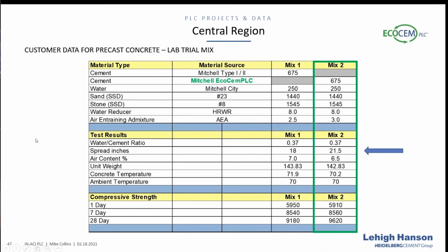This is a trial mix that we did in our lab at the request of a customer, where we wanted to evaluate how PLC would perform in a precast mix. So we took this precast mix design and replicated that in our laboratory, and we used Mitchell type 1-2 in mix 1, and mix 2 was the EcoCem PLC. Pretty heavy cement doses at 675, again, a precast where they're interested in some early strength gain. One of the interesting points for me was that with the PLC, we saw about a 3.5 inch increase in spread. To me, that kind of opens up some interesting options.